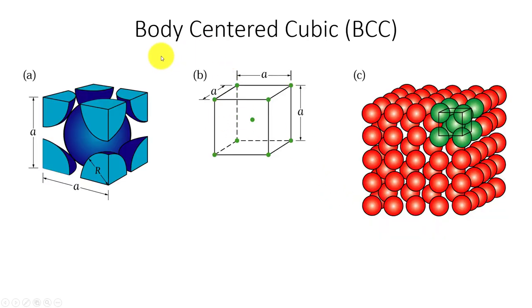When we talk about these grains, we need to understand what's happening in steels in terms of lattice structures. There are some terms you need to have. Body centered cubic — BCC. What we're saying here is we're going to have a square structure equal in all dimensions. We're going to have an iron atom at each corner, as well as a full iron atom in the center. If we took an imaginary knife and cut that thing up, we're going to see an eighth of an atom at each corner and a full atom in the center. Representatively, we have two effective atoms in one unit lattice structure.